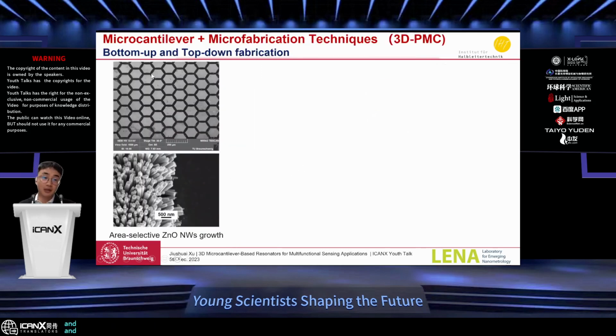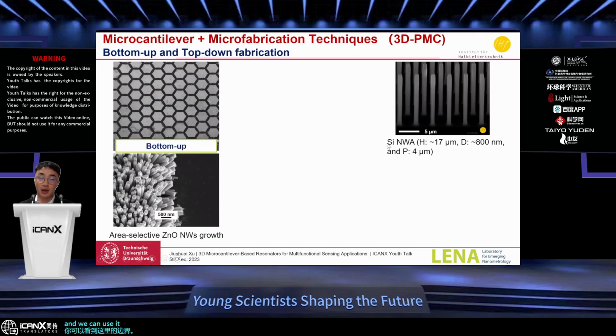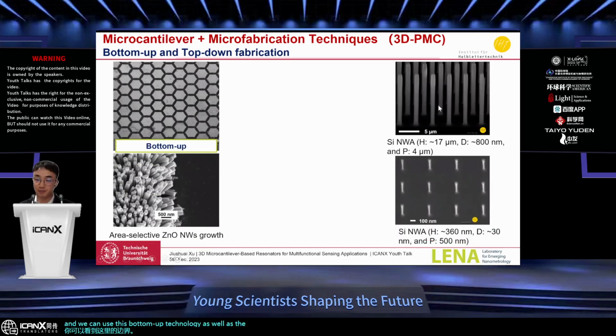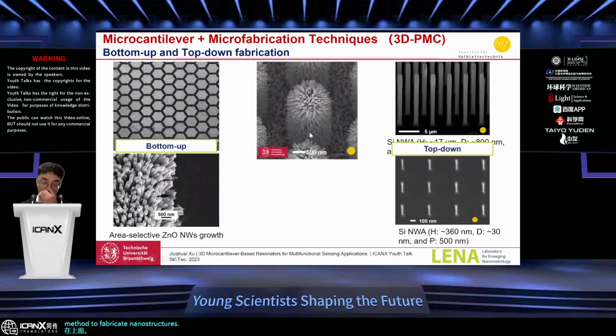Another method of nanofabrication is bottom-up, where you deposit or grow nanostructures on the substrate. We also did area-selective zinc oxide nanowires by chemical bath deposition and sputtering. You can control the wires very well in defined patterns, and you can see the border here. We can use this bottom-up technology as well as the top-down method to fabricate nanostructures. For example, here you have Christmas tree-like nanostructures, a combination of top-down and bottom-up. You can create some interesting 3D structures.